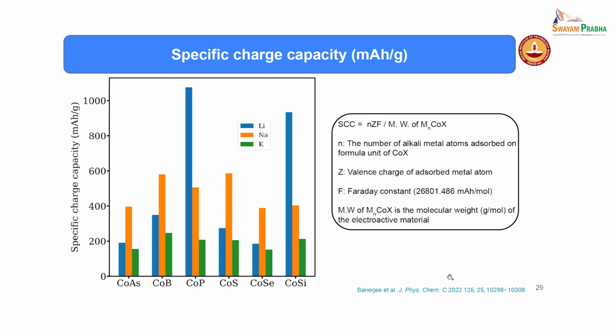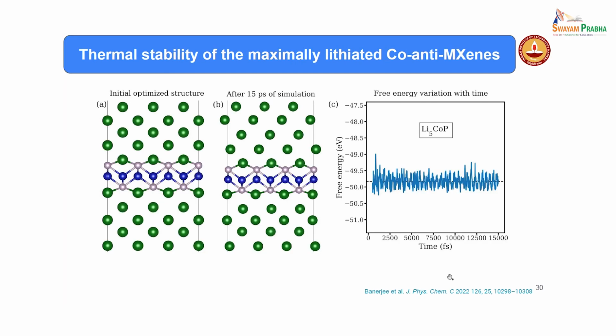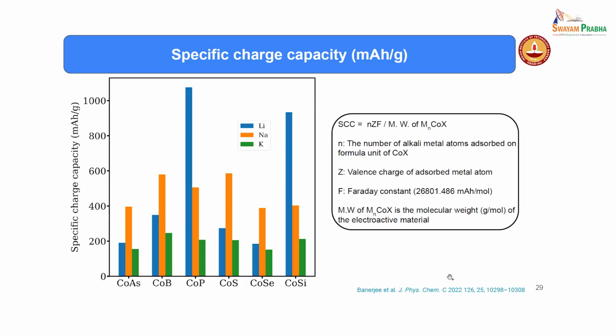So similarly, once you identify a material, like for example cobalt selenide, and if you know how many atoms are adsorbing, then you can even calculate whether potassium will be the one which will be the least, or the other ones, simply based on the number of atoms that are adsorbing and the molecular weight. So what we are doing here from first principles is to obtain the adsorption energy, and that is what is helping us to identify how many atoms we can actually adsorb. All other things are constants only. So as such, we find that there are a few materials that can have very high specific capacities for lithium. Majority of them have very good specific capacities for the case of sodium. So that's the important point that we learned. Those materials that have low voltage and also high specific capacity are the best materials that we can use as the anode materials in batteries.